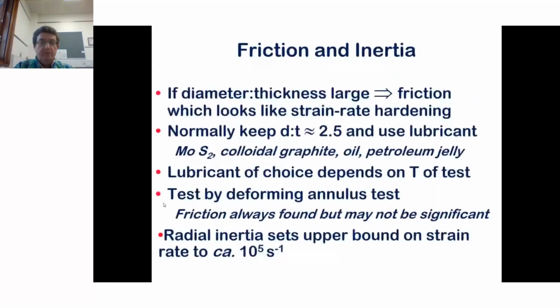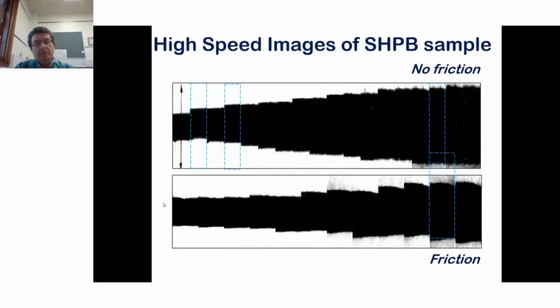We can discuss friction and inertia. We can talk about changing temperatures. There are a number of factors to take into account. If you're worried about friction in your sample, I would say do the experiment without lubrication, do the experiment with lubrication between the sample and the bars. See if there's a difference. No difference means friction isn't a big effect. It's pretty straightforward. And here are some high-speed images of a split Hopkinson pressure bar.